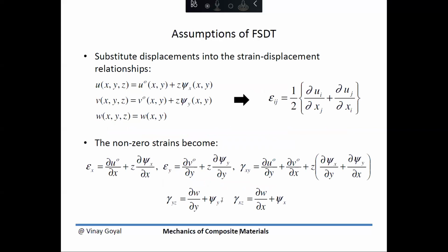If we were to substitute the deflection assumptions into the strain-deflection relationships, which were previously described for linear geometry, not for nonlinear geometry, if we were to substitute these deflection assumptions into these 6 components of strain, then we will come up with 5 non-zero strains. You can see them here: epsilon XX, epsilon YY, gamma XY. These 3 correspond to the in-plane strains of the composite laminate. While these 2 strains used to be 0 in classical plate theory, they're no longer 0.